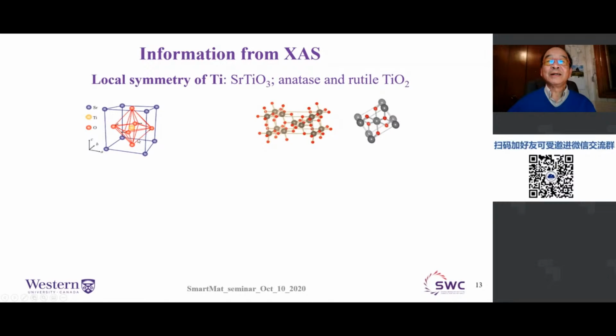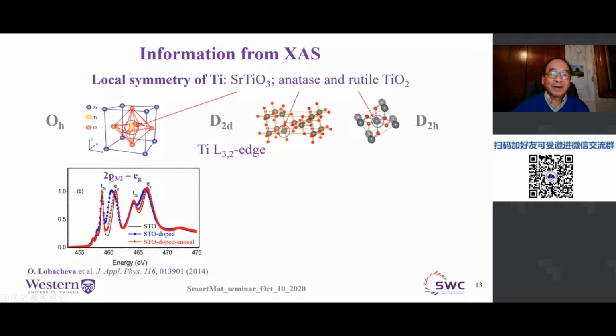So let me take titanium ion, in this case, in three different environments. Say in strontium titanate, it is in an octahedral crystal field. And then in titanium oxide anatase and titanium oxide rutile, they are distorted, but they are distorted differently. As a result, the spectrum looks characteristically different. If you look at the so-called L2,3 edge, we're exciting the 2p electron into the d states in the case of titanium. So here you have this 2p hole to eg transition. Let's just focus on the transition to the eg orbital.